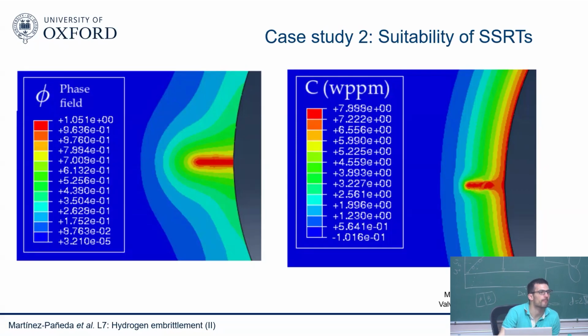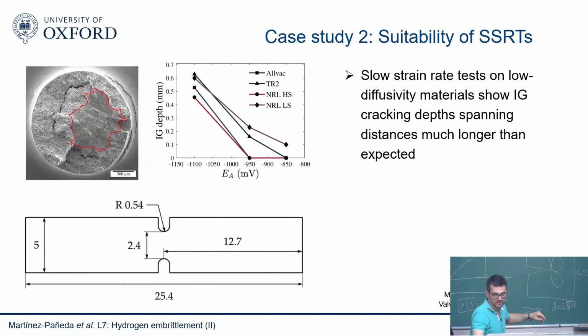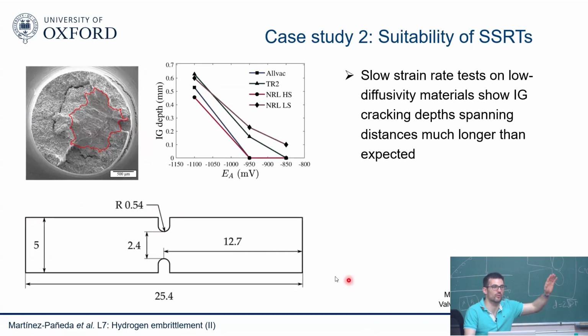Of course. The concentrations that you have in terms of initial boundary conditions, what are they for this problem? In this case, we reproduce the same as in the experiment. The way they run their experiments is that they pre-charge for 2 hours, if I remember well. They expose the sample to an electrochemical environment. They have more or less quantified what hydrogen concentration belongs to that electrochemical environment through a permeation test. It's not perfect, and then they start pulling. So we prescribe a hydrogen concentration here, we let the model run with our mechanical load for 2 hours, like they do, and then we start pulling. That's the idea.